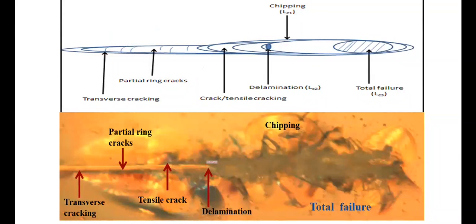Okay. Apart from that, for any coating we have to see the mechanical stability of the coating. So we do a scratch test using one of our instruments, a micro scratch hardness test, and that is one of the very important tests in the coating industry. So now, when we scratch, we can see that transverse cracking is taking place, partial ring cracks, tensile cracks, delamination takes place over here, and total failure takes place over here.